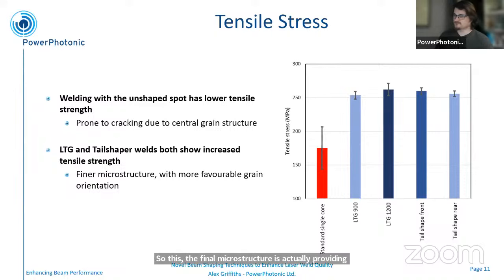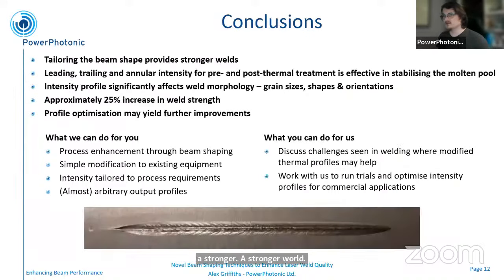So in conclusions, we have shown that tailoring the beam shape provides stronger welds, and that this leading, trailing, or an annular intensity profile for pre or post thermal treatment stabilizes the melt pool and improves the weld strength. These significantly affect the weld morphology, grain sizes, shapes, and orientations are changed, and we've achieved approximately 25% increase in the weld strength. This is only a starting point. We've really just shown that the beam shaping gives you an improvement.